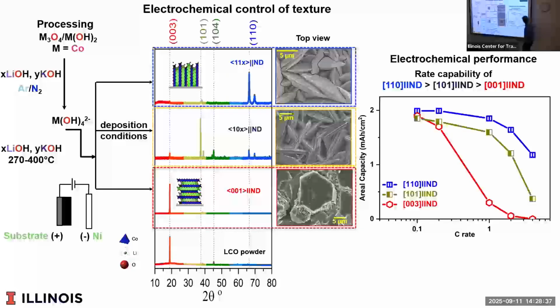And in fact, here, this is C rate. If you're a hobbyist with a drone or something, C rate is how fast you can charge or discharge. 1C would be to take 1 hour to discharge it. And so a drone battery might say 20C or 50C. That means you can really get a lot of energy out in a few minutes. But if I take it and orient it the right way, I get basically all the energy out. And if I turn it the wrong way, I basically don't get any of the energy out.